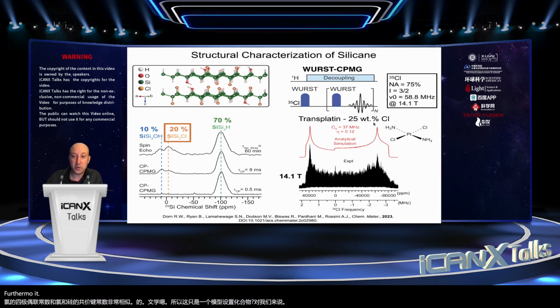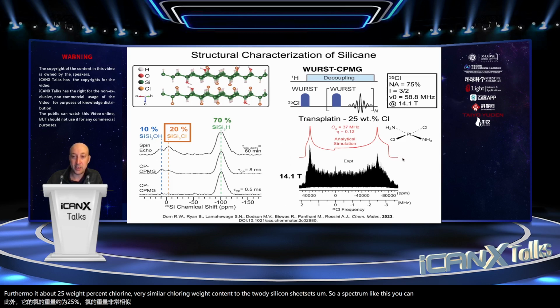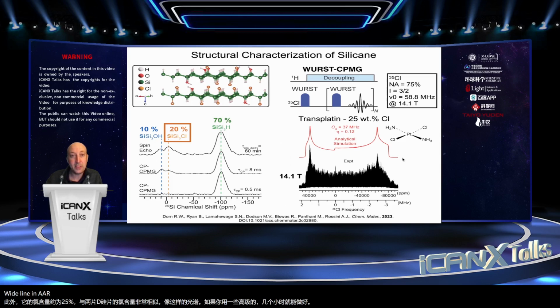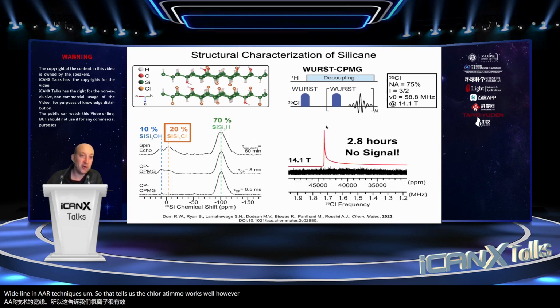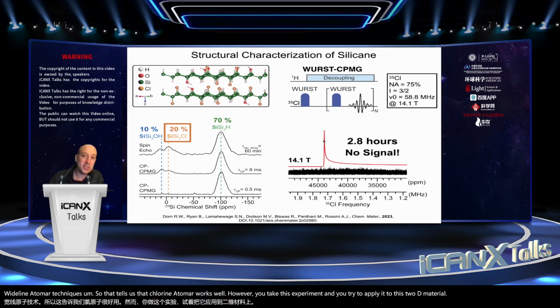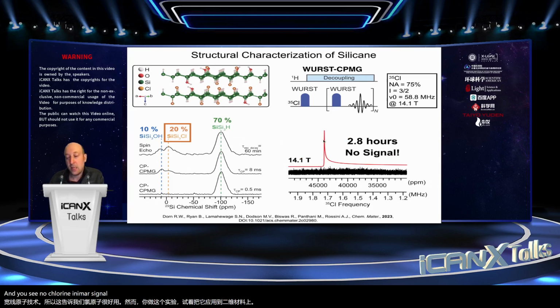Furthermore, it's about 25% weight chlorine, very similar chlorine weight content to the 2D silicon sheets. So a spectrum like this, you can get in a couple hours if you use some advanced wideline NMR techniques. So that tells us that chlorine NMR works well. However, you take this experiment and try to apply it to this 2D material and you see no chlorine NMR signal.